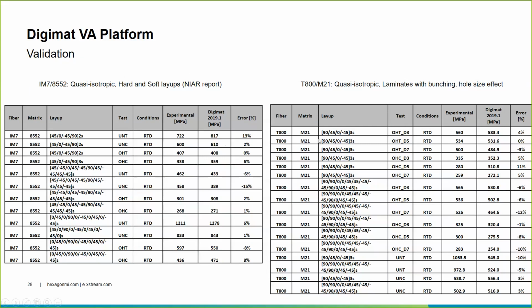And here you have the result for the T800 M21, so with quasi-isotropic layup, with laminate with bunching. So typically the bunching is this type of laminate where we have 2 plies at 0 consecutively. And then also the hole size effect. You have here some configurations where you have 3 dimensions of the hole. So all those ones give really acceptable results.